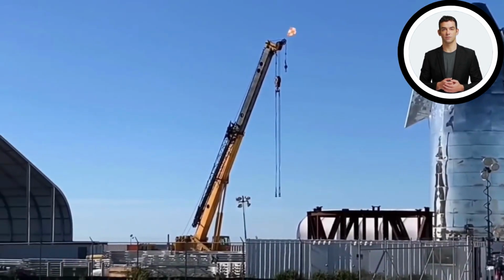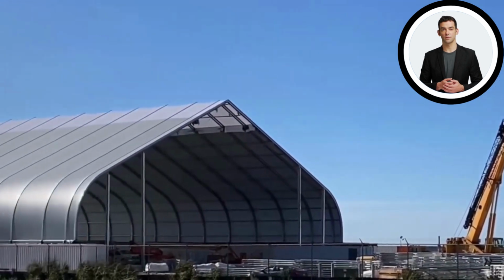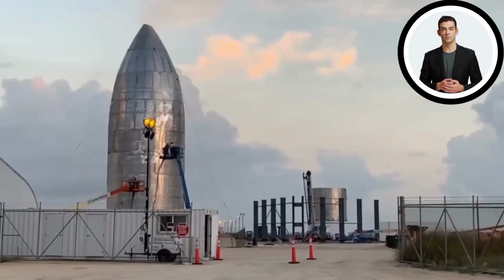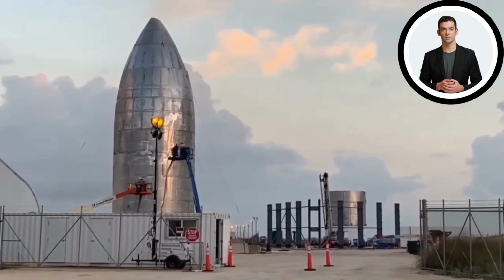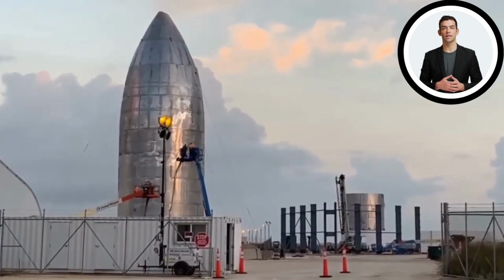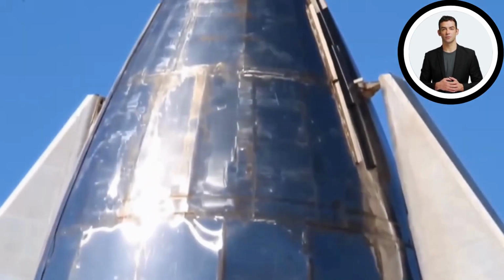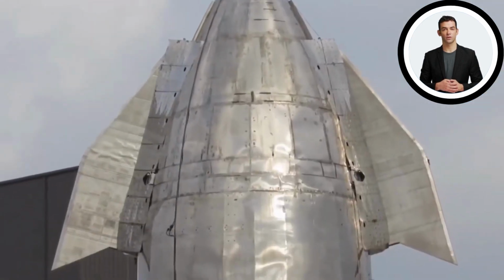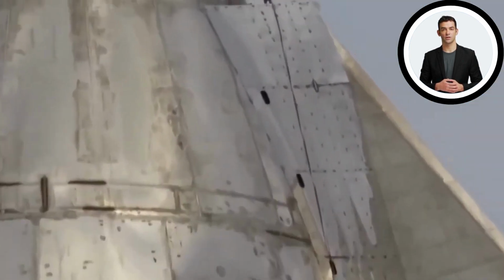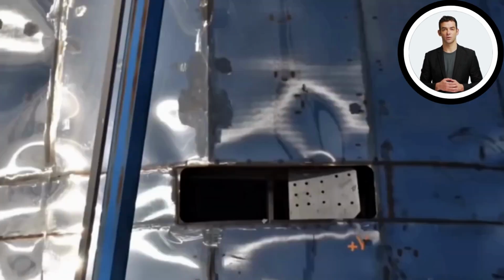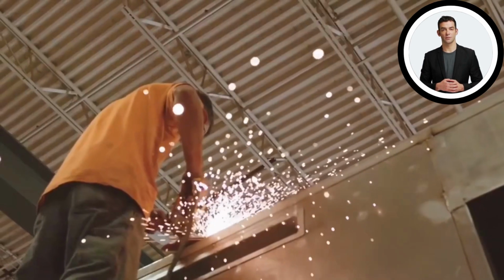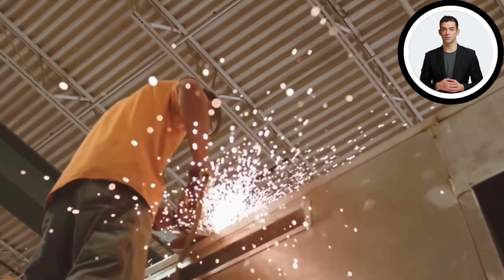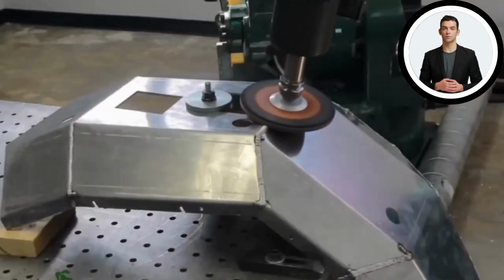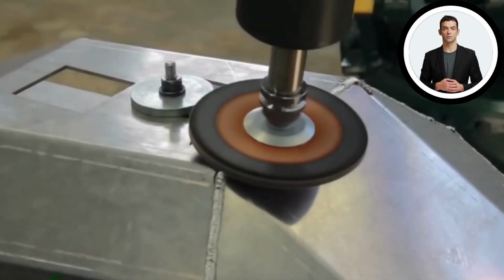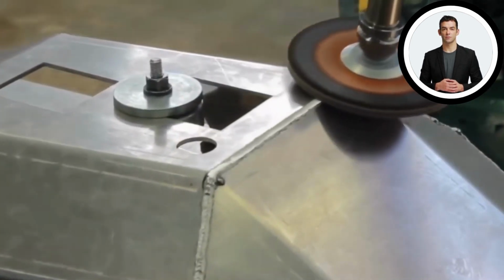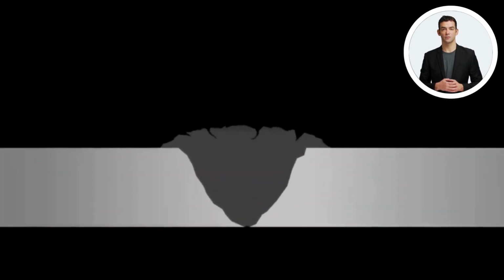Naturally, the appearance of the spacecraft was so bad that the welds on the first Mark I prototype were badly corroded and had cracks and roughness on the surface. In theory, each weld should be as strong as the metal around it. But early spacecraft tests showed that the Mark I exploded when one of the horizontal welds failed and allowed a bulkhead to fail. In a 2019 tweet, Everyday Astronaut asked Elon if there was any significant difference in welding techniques between the Mark I prototype and Mark II prototype.